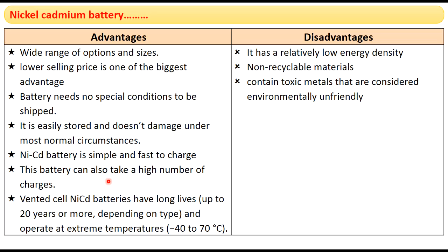Nickel cadmium battery has a high cycle life. That is another advantage. Vented nickel cadmium batteries, they have long lives. Some vented nickel cadmium batteries we can use up to 20 years. And these vented nickel cadmium batteries can be operated at extreme temperatures from minus 40 to 70 degrees centigrade. These are the advantages of nickel cadmium battery. Disadvantages of nickel cadmium battery are the energy density of nickel cadmium battery is low compared to other batteries, and we cannot recycle the materials of nickel cadmium battery. Another important disadvantage is nickel cadmium battery contains toxic metals. Disposal of nickel cadmium battery will damage the environment. So this battery is not eco-friendly. These are the disadvantages of a nickel cadmium battery.